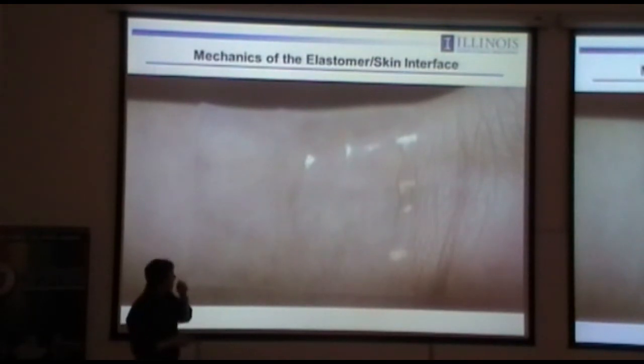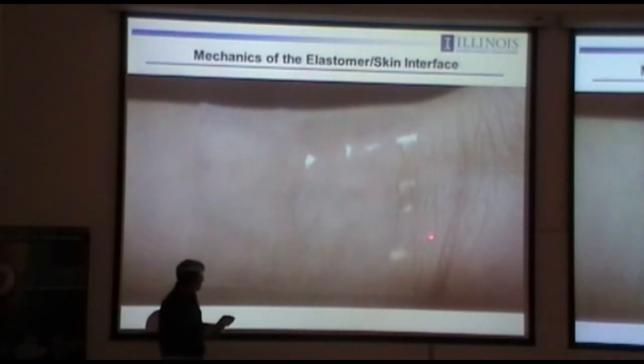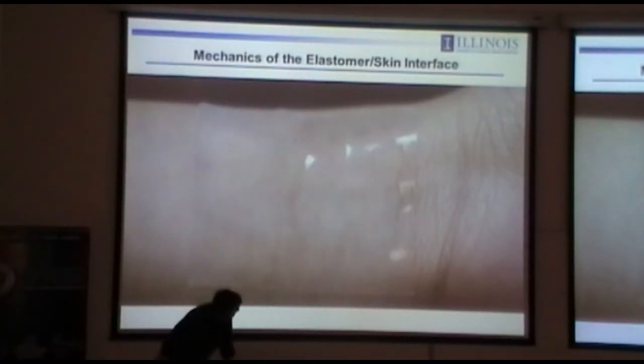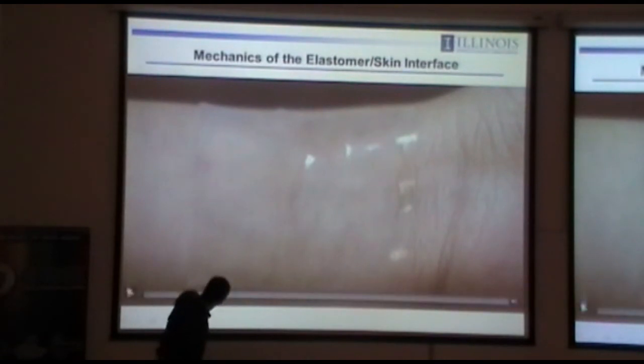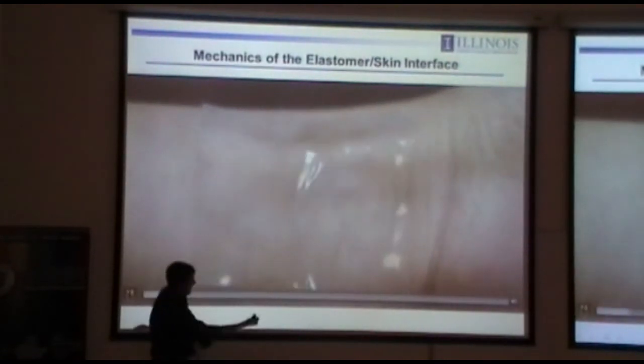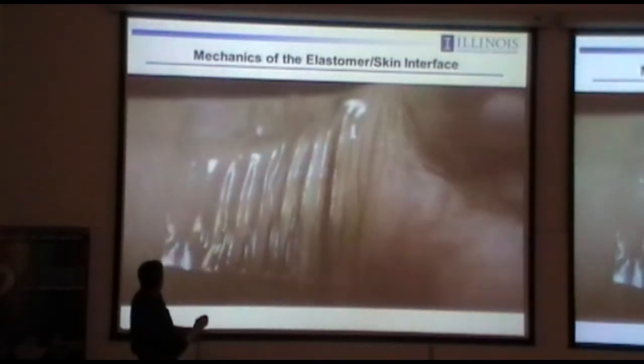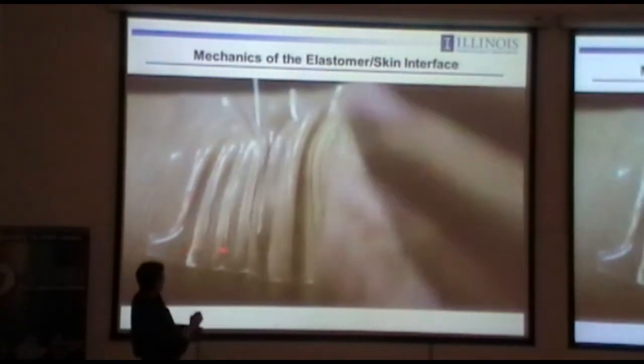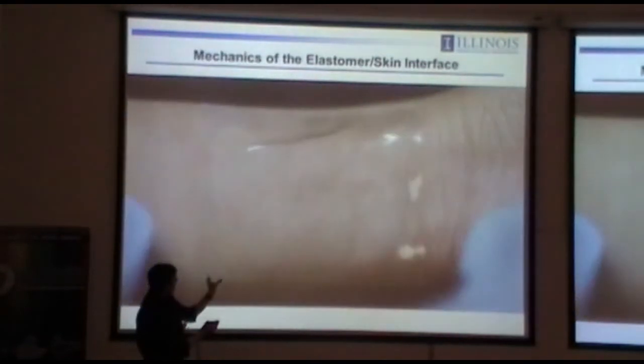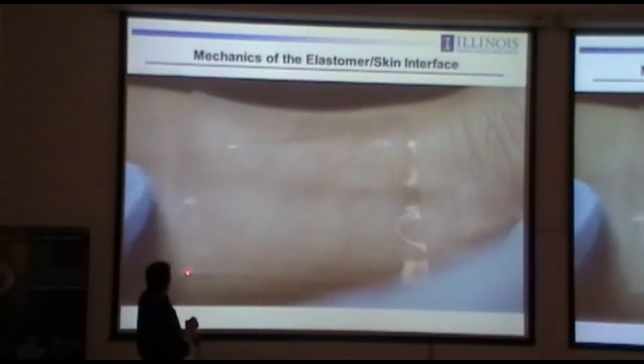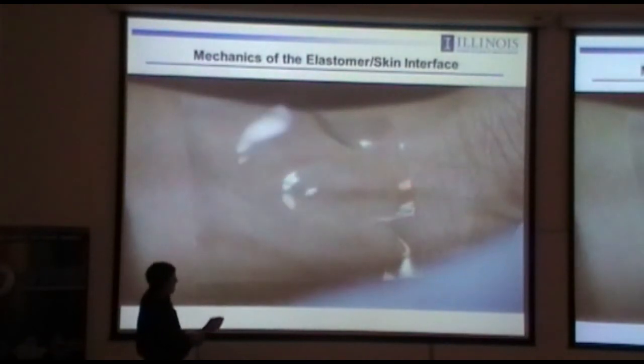And you can kind of see that qualitatively in experiments that you can do just with a sheet of rubber. So here's a sheet of rubber, it's polydimethyl siloxane, with a certain cross-linking density that yields a modulus of about half a megapascal or so. And we have a thickness of about 100 microns. You can laminate that onto the skin, it's no problem. You put it near the wrist region, and then you can flex the wrist, and you'll see the physics that I just mentioned to you. You flex it, that's sort of the bending motion. And what you see, there's the delamination, starts there, it's starting to flake off. Then you can pull the skin in tension. Again, you see delamination starts at the edges and then runs across the interface.